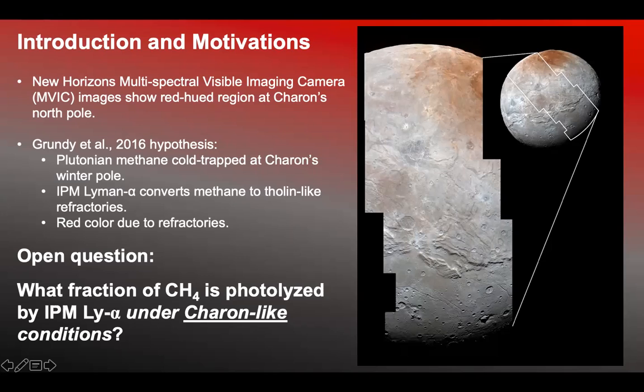And the red color of this deposit is due to refractories of the photolyzed methane. So in other words, methane is bombarded by Lyman alpha radiation. I'll show more about that in the next slide. And it is converted into these more complex refractories that have that distinct red color. So the open question here, before really saying what's real and what's not on this hypothesis, is: what fraction of the methane is photolyzed by the IPM Lyman alpha under Charon-like conditions? And there's where you have to do laboratory experiments to figure that out.